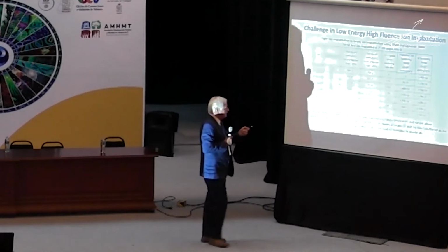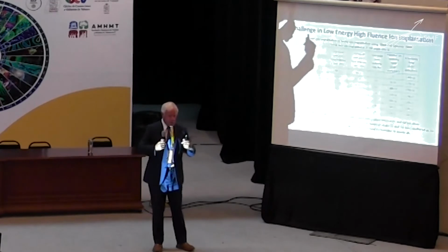And here, this is the target atom sputtering yield per ion that comes in. Every ion that comes in knocks out 5.46 ions. One ion in at that energy and that mass knocks out 5.46. So you have to take this into account. That's why we're using this special program that allows us to take care of sputtering. Next slide.